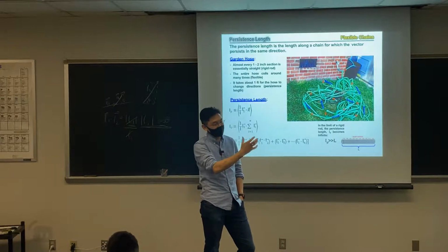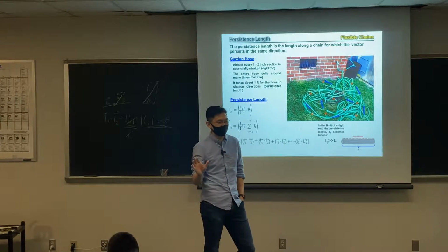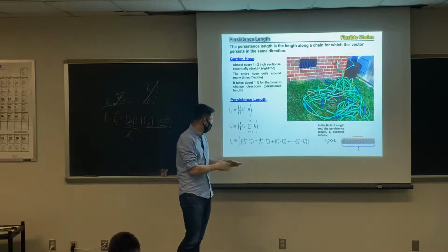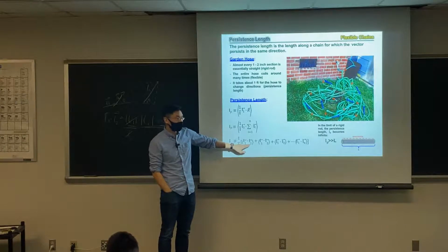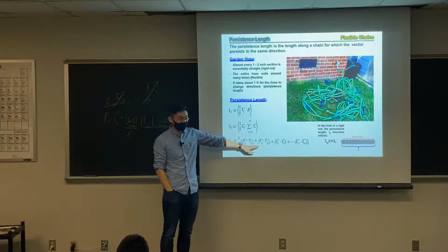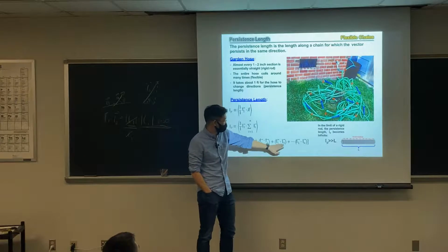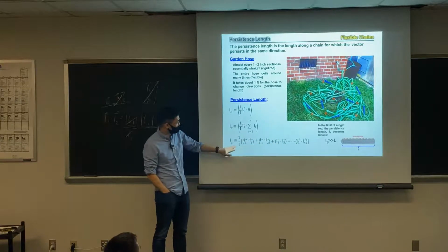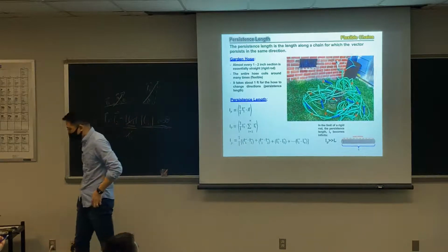The second bond basically says, I don't care what my predecessor thinks. I can go anywhere I want. I'm not influenced by my predecessor. So if you look at this equation, L1 dot L1 is going to be L squared, and the average of L1 dot L2 for a freely jointed chain will be 0. This will be 0 again. So it's also reflected in this equation: for a freely jointed chain, LP will be equal to L squared divided by L. That's basically one bond length.